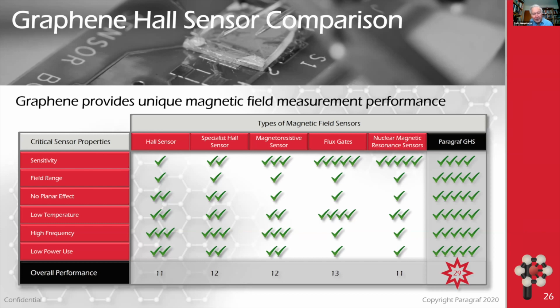But on everything else in this table, the field range, no planar effect, low temperature operation, high frequency, low power use, we're much better than any of these in these other quantities. So I'm speeding up a bit in my talk. This is very qualitative, but if you add up the number of ticks, which gives you sort of overall performance, then we have 29 ticks with a graphene Hall sensor compared with 11, 12, 13 and 11 for others. So its overall performance is much better than any other Hall sensor in the world.